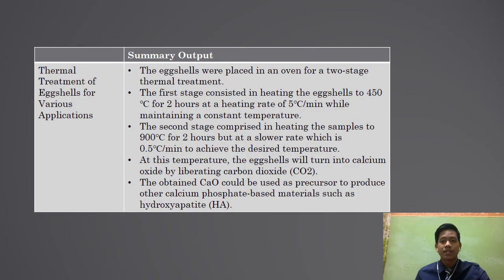This slide indicates the literature review of the thermal treatment of eggshells for various applications. The eggshells were placed in an oven for a two-stage thermal treatment. The first stage consisted in heating the eggshells to 450 degrees Celsius for 2 hours at a heating rate of 5 degrees Celsius per minute while maintaining a constant temperature. The second stage comprised in heating the samples to 900 degrees Celsius for 2 hours, but at a slower rate, which is 0.5 degrees Celsius per minute to achieve the desired temperature.